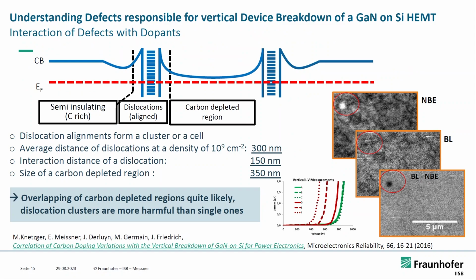And we were expecting that there are changes in the insulation buffer. And what we found - you have seen the picture of the gallium nitride before, where we have seen the dark spots. You may remember, so in the gallium nitride and silicon you have many of such dark spots. And these dislocations become really close together.